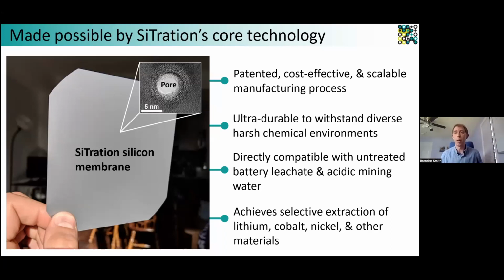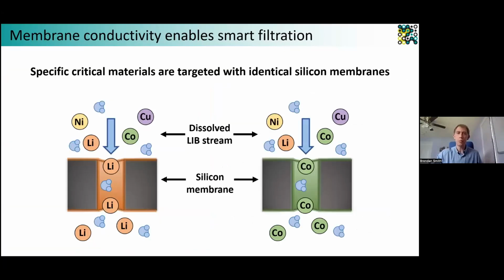And lastly, and really importantly, it's electronically conductive. As you might guess with silicon, we can tune that broadly as well over 3 or 4 orders of magnitude of electrical conductivity. And it turns out this allows us to really selectively grab out via specific processes the important materials, namely lithium, cobalt, and nickel. So those three things combined together give us a uniquely differentiated value, which we're leveraging then in the critical materials recovery space.